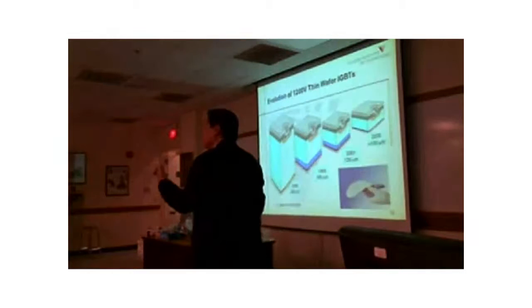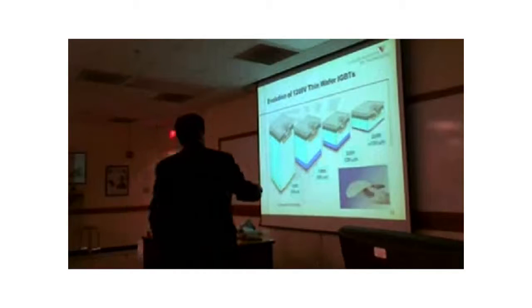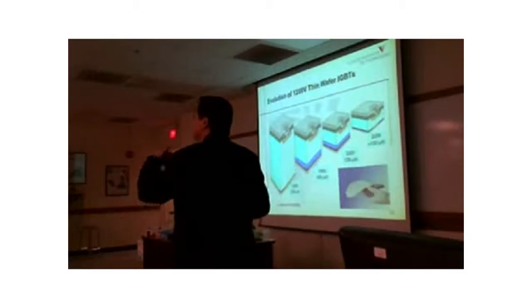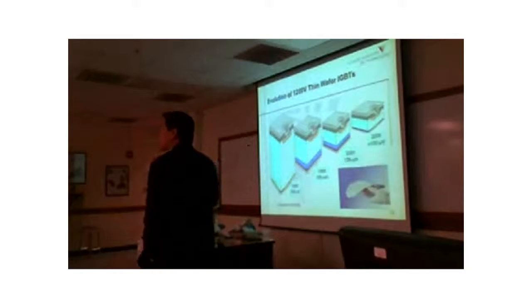In the old days, back in 1995, we had float zone IGBT with a 300 micron thickness. And gradually over the years, you can see right now it's only 100 microns thick. And if the thickness goes down to 60 microns, the silicon wafer won't be rigid anymore. It's pretty much like a taco. You can kind of roll it, putting all the goody stuff on top. Also, the trick is how to grind the wafer so thin and still continue processing it without breaking the wafer. Nobody talks about that. It's an industrial secret. Everybody has their own secret. There's no publication on that.